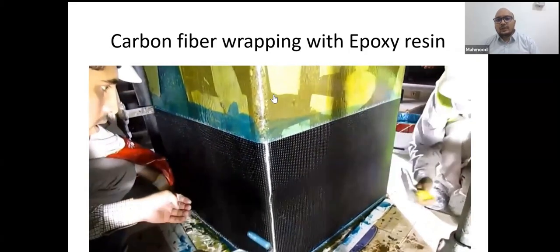They have repaired the substrate to make it smooth. They have filled the blowhole and pinhole with the help of epoxy putty and made the surface smooth. Then they applied the epoxy primer. You can see this blue color one. Okay. Then they wrapped it with the carbon fiber.